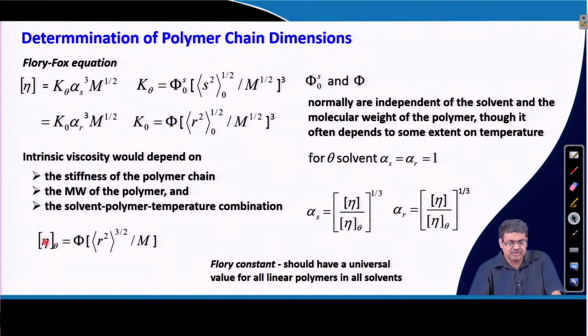So, if you know the intrinsic viscosity in theta solvent, then this expression can be written like this, where phi is the Flory constant, and this should have a universal value for all linear polymers in all solvents.